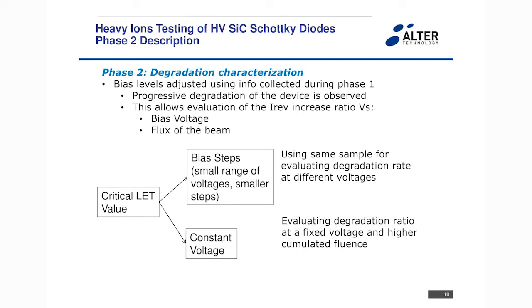Well, we never arrived to the 700 bias step. This is performed using all the part types we have. So you have an idea of where you have a completely destructive damage of each part type. In phase 2, we adjust the LET to a couple of values, higher values than